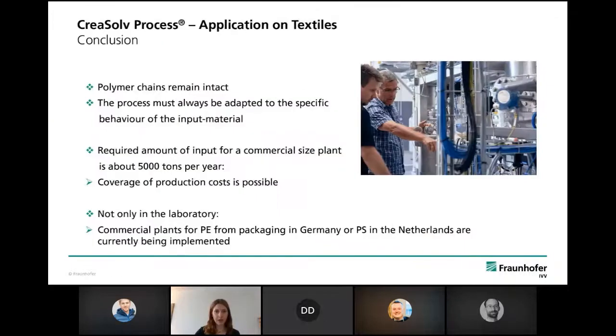So, yes, I am already at my conclusion. The things I want you to remember are that the CreaSolv process is not a chemical recycling process, but the polymer chains remain intact. And that there is not one single form of the CreaSolv process. The CreaSolv process always has to be adapted to the material and how it behaves in the process. And so it always has to be checked what material should be dissolved and what is better to be in the residue. So we always have to check every single input to see how we treat it the most efficiently.